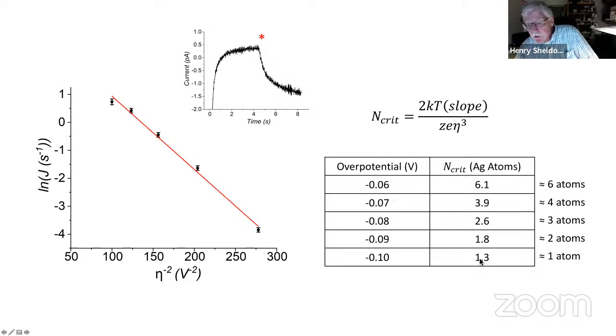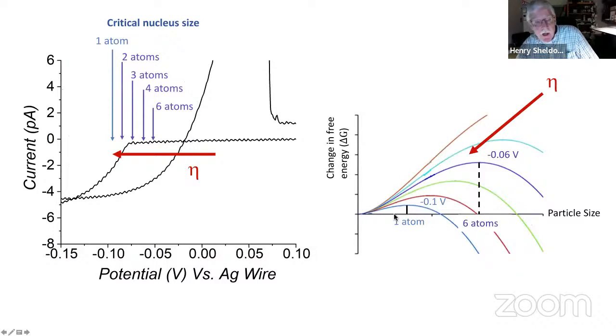As you go to a higher potential, this number decreases and decreases. Of course, this has got to be a discrete number. So we assign, I mean, we could be wrong, but we think this 6.1 really corresponds to 6 atoms, and the 3.9 to 4, et cetera. So we're calculating the size of the nucleus, but in terms of the number of atoms. And there are no assumptions in this measurement about the surface tension between the silver and the solution or the geometry of the nucleus. This equation just gives you absolute numbers of atoms as a function of your overpotential. And so now you go back to the basic science.